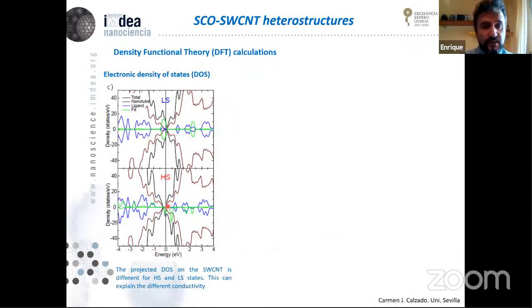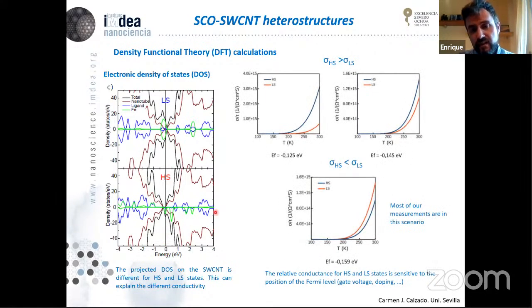They have also calculated the density of states and the density of states projected on the carbon nanotube, and they see how it is indeed different for the low spin and the high spin state around the Fermi level. So if they now calculate the conductance as a function of the temperature, they see more or less what we see: the high spin state and the low spin state produce a different conductance in the carbon nanotube. They see actually the opposite. They see that the high spin is conducting more than the low spin state.